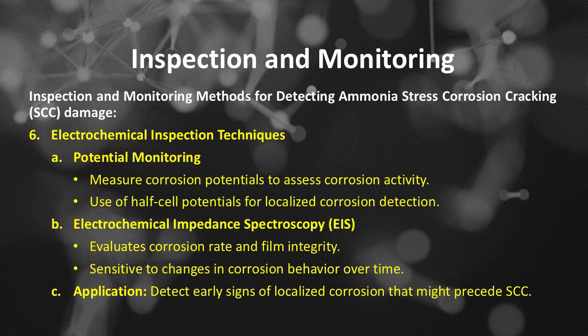Number 6 of inspection and monitoring methods for detecting ammonia stress corrosion cracking damage is electrochemical inspection techniques. Number A, potential monitoring, includes measuring corrosion potentials to assess corrosion activity, and use of half-cell potentials for localized corrosion detection. Number B, electrochemical impedance spectroscopy. It is used to evaluate corrosion rate and film integrity. It is sensitive to changes in corrosion behavior over time. Its application is to detect early signs of localized corrosion that might precede SCC.